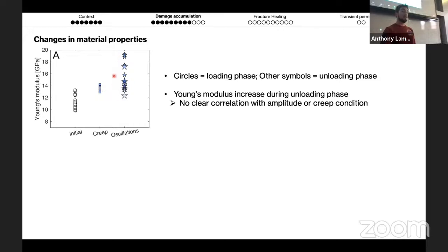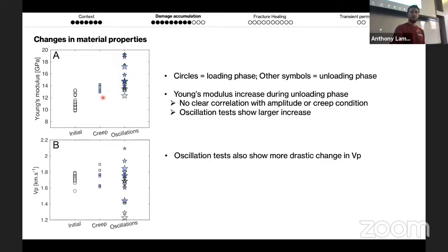Also, there doesn't seem to be a clear correlation between either creep or oscillation. It just increases during the unloading phases. This change is bigger during the oscillation test. So if there is damage that is being created, this would create more damage than this.